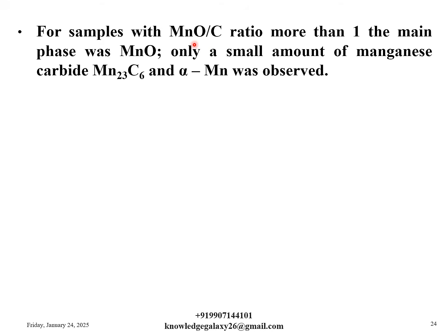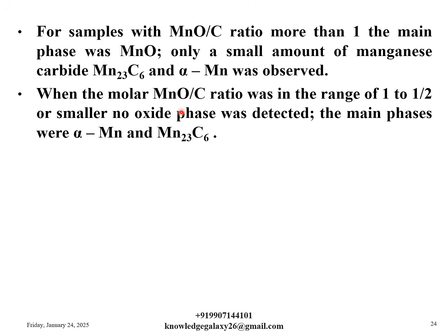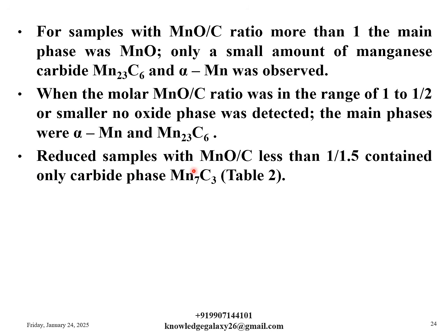For samples with MnO by C ratios more than 1, the main phase was MnO. Only a small amount of manganese carbide Mn23C6 and alpha manganese was observed. When the molar MnO by C ratio was in the range of 1 to 1 by 2 or smaller, no oxide phase was detected. The main phases were alpha manganese and Mn23C6. Reduced samples with MnO by C less than 1 by 1.5 contained only carbide phase Mn7C3, which is shown in table 2.